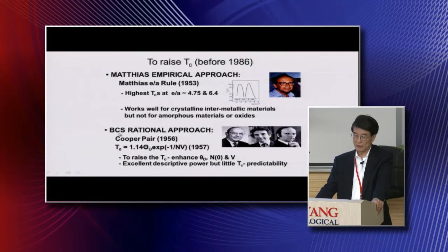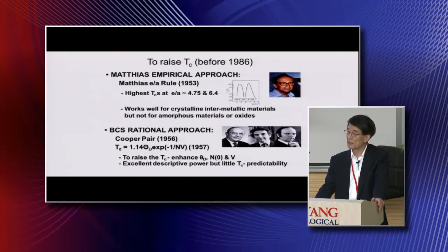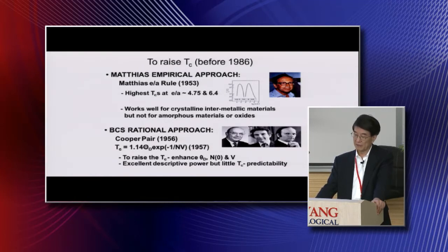The second approach is the BCS rational approach, based on this simple expression. That is, TC is proportional to the characteristic temperature, in this case because of the electron-phonon interaction, the Debye temperature, times exponential of minus 1 over N V. N is the density of states, and V is the attractive interaction. So to raise the TC according to this formula is very simple. We just increase the Debye temperature, density of states, and attractive interaction. It turns out all these parameters are coupled to each other, and that makes it a little bit hard. And this formula describes superconductivity very well, but it cannot predict the TC.